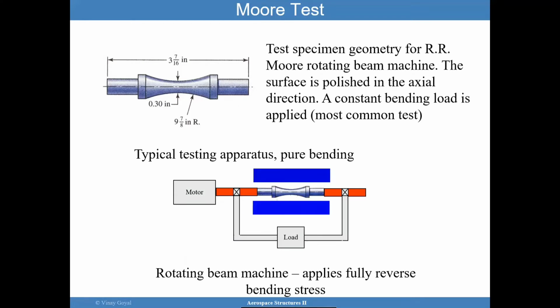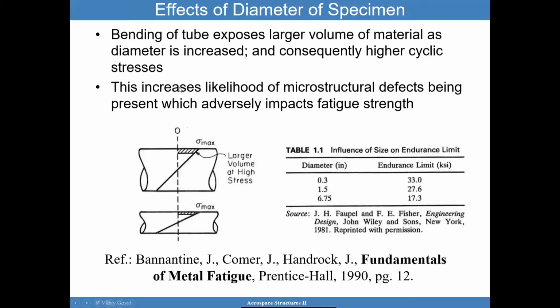So the Moore test is another type of test that was considered. The surface is polished again in the axial direction. A constant bending load is applied. So basically you have this motor, you have this load applied that causes bending to the sample, and then this motor causes rotation of the sample, causing this fully reversed bending stress. So this is one of the approaches that's used, and this is your standard geometry for this kind of test.